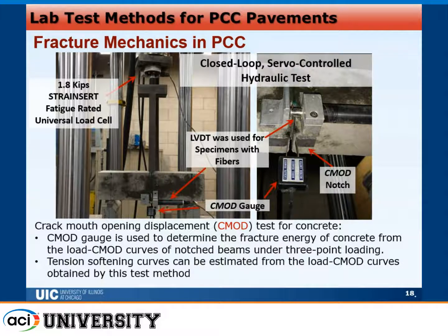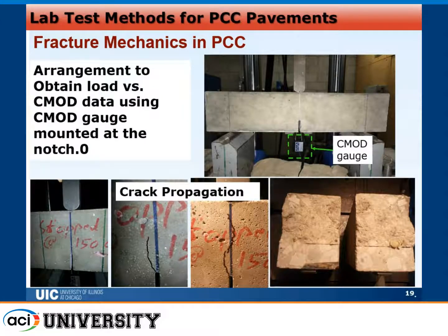The range of the CMOD is around 10 millimeters. The ones with fibers, as you will see later, will go up to 25 millimeters of crack mouth opening displacement. However, the ones without fibers will split into 2 pieces at around 1 millimeter. So this CMOD gauge controls the loading of the machine, and it's three-point loading here, and another representation here for the shape of the failed surface.